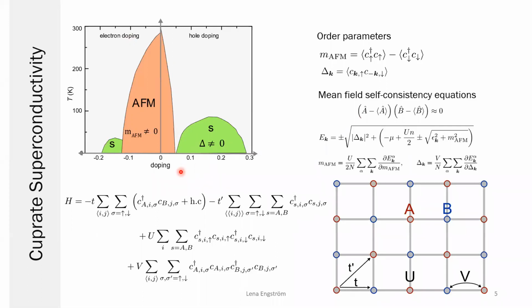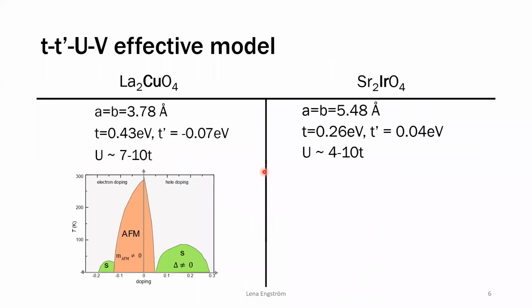And we can see that the method of doing this is that from writing down the free energy, we can find that the minimized solution is found when we have a set of coupled mean field equations, or self-consistency equations, which when all of these are fulfilled, we have found a minimized state. Now, to see that we have a prediction for superconductivity in the iridates, we can just compare the two materials.